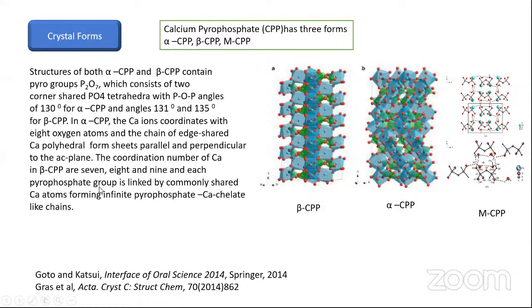The structures of both alpha CPP and beta CPP contain pyro groups, P2O7, which consist of two corner-shared PO4 tetrahedra with a P-O-P angle of 130 degrees in alpha CPP, and angles of 131 and 135 degrees for beta. Now in alpha CPP, the calcium ions coordinate with 8 oxygen atoms, and a chain of edge-shared calcium polyhedra forms sheets perpendicular to the AC plane.